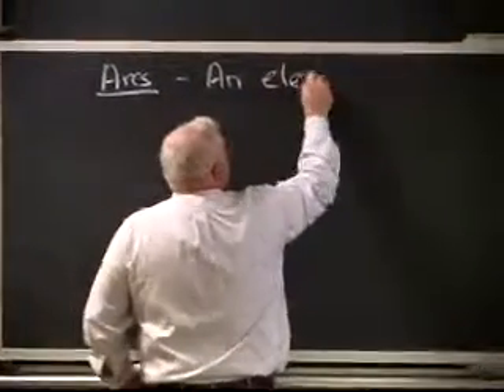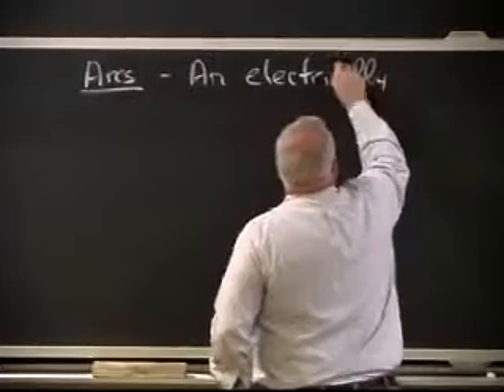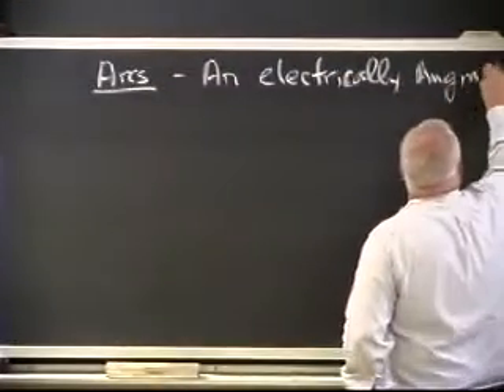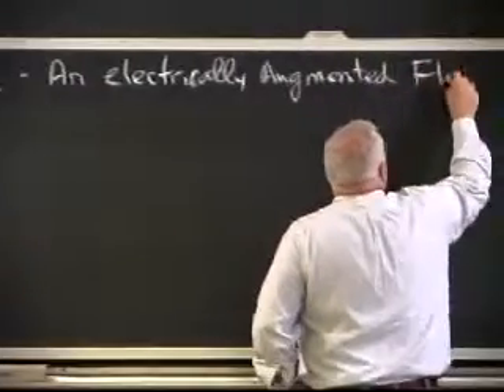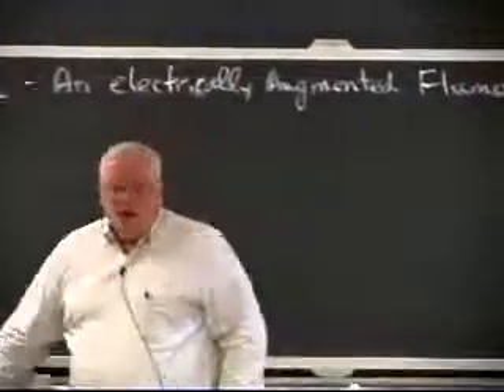Okay, arcs are electrically augmented flames. This is a Tom Eager definition. You won't find this anywhere else. We said we have a boundary layer, and that limits the heat transfer to the surface of something. The maximum heat intensity I can get, typically with a flame, a pre-mixed flame, is about 1,000 watts per square centimeter. With a jet burner, where I get very high velocities, but not higher temperatures, right? Because it's still maximum near the adiabatic flame temperature. But a jet burner, I'm igniting inside a constant volume, and so it shoots out at very high velocity. I might get 2,000 watts per square centimeter as a heat intensity on the surface with a jet burner.